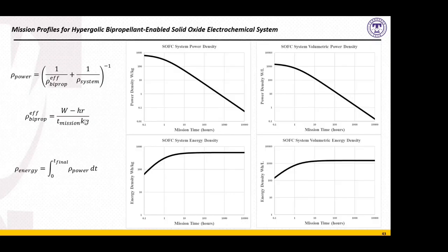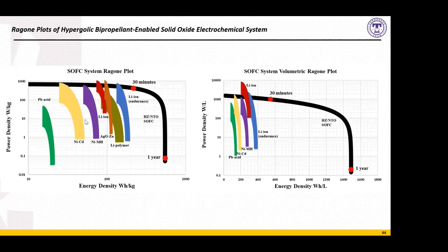When we graph the energy densities and the power densities together, we have these Ragone plots. A Ragone plot compares the energy density and power density of a system. And we find that for the hypergolic bipropellant-enabled system, at 30 minutes of continuous operation, we've pretty much reached our break-even point where we are now beating the performance of the batteries. And these are here laid out, the current battery technologies that are oftentimes used. So at 30 minutes, we're beating the battery.